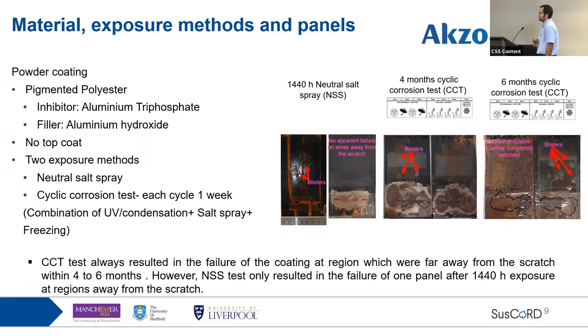Going through the materials, what I have investigated and characterized are one-layer polyester powder coatings, which were prepared by AkzoNobel and exposed at AkzoNobel and then sent to me. The inhibitor in these coatings is aluminium triphosphate, but we also have fillers such as aluminium hydroxide and a few other fillers as well. After preparing these panels, the panels usually are scratched. The scratch is here, but in these panels, the scratch area is removed for measuring the corrosion underneath the coating. And then they are exposed to the neutral salt spray test, which runs continuously for 1,440 hours.